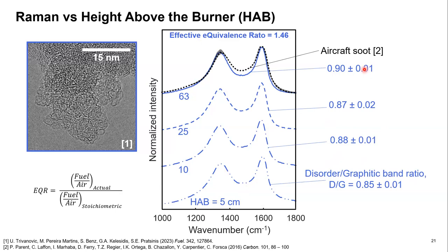Once again, we want to compare to the literature on aircrafts. This dotted line shows the Raman spectra from aircrafts at several different thrusts, and the shaded area represents the variation between these different engine thrusts. And what we see is that once again, our data at the exit of the burner is in excellent agreement with that from real aircrafts. And I'll point out that this is just one exemplary equivalence ratio of 1.46, and also holds for the others.